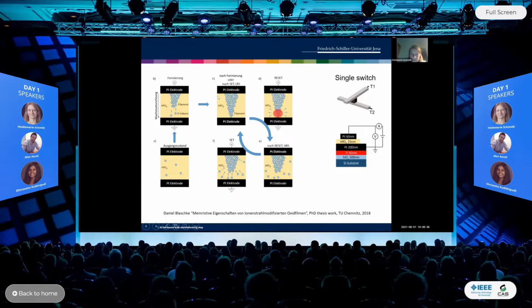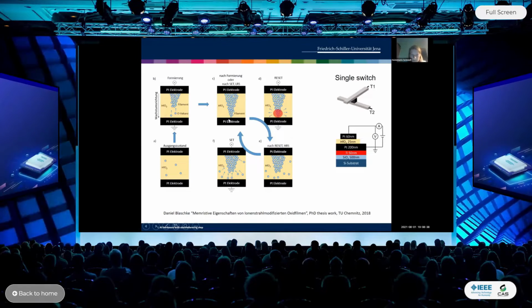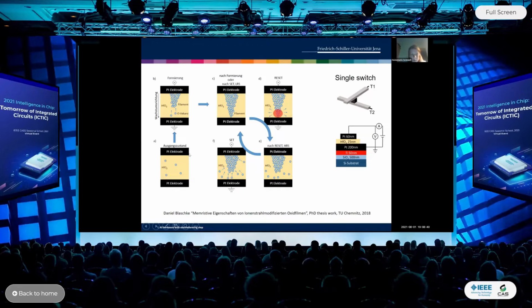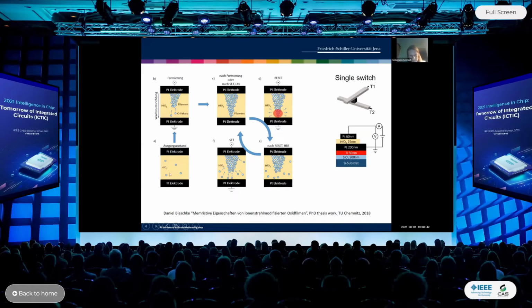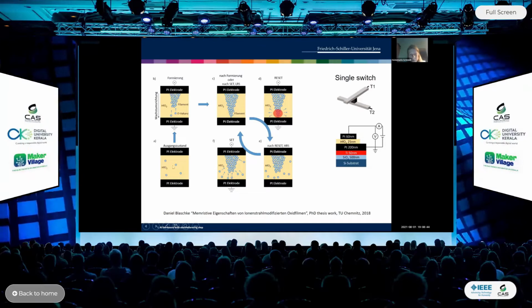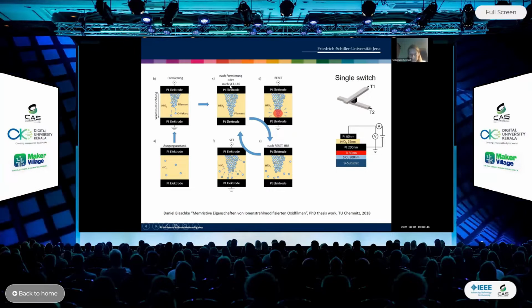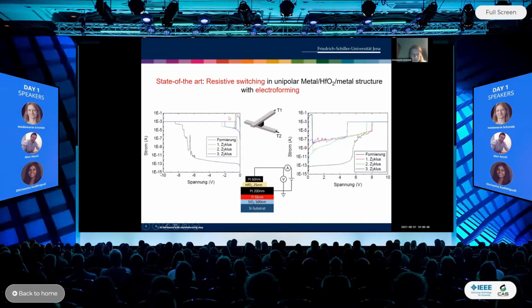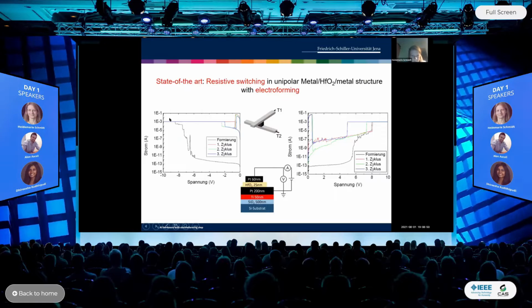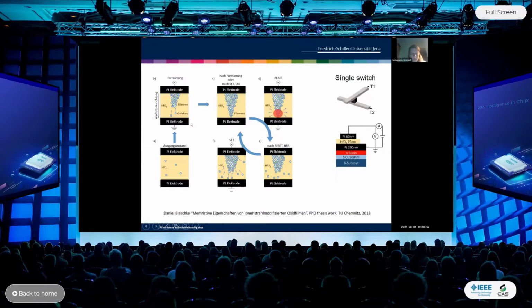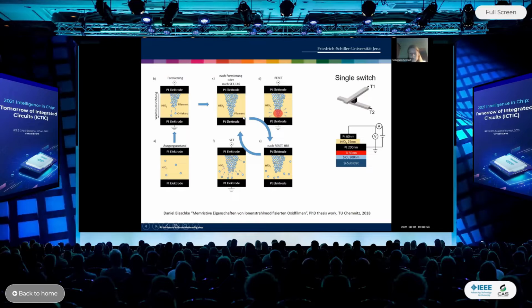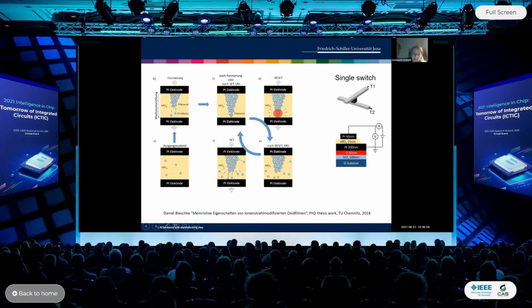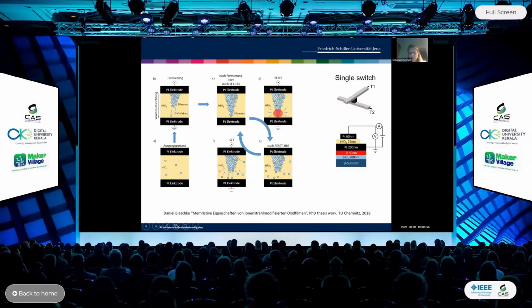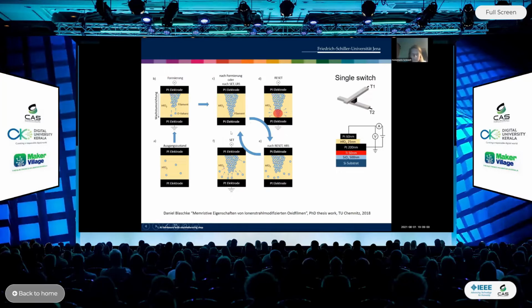And if this is done, you have formed this filament, and then the system is switched from the high resistance state, where there's no filament bridging top and bottom electrode, to the low resistance state. This is the first step we see here. This is the first bridging step. And then it goes further. Then you can interrupt this filament by applying a very small bias. This is called reset, right?